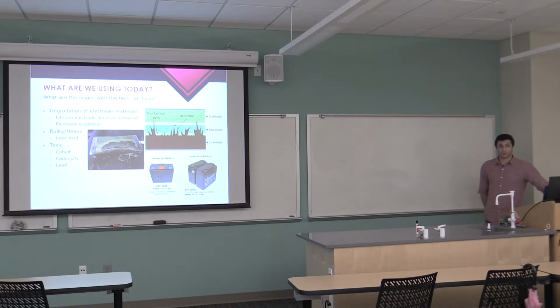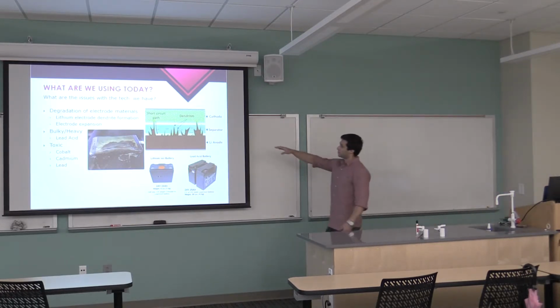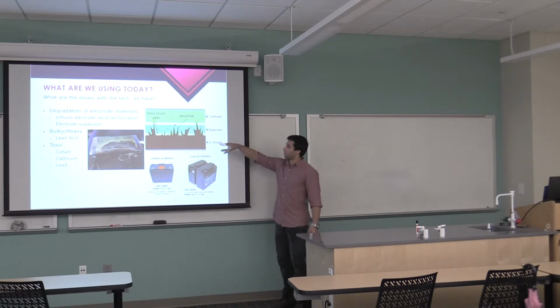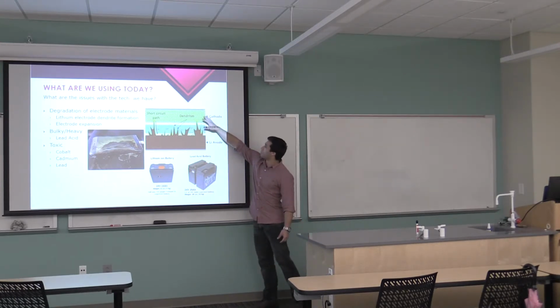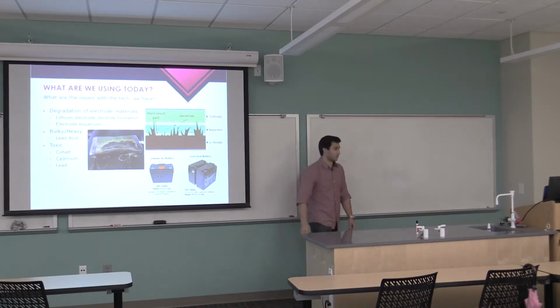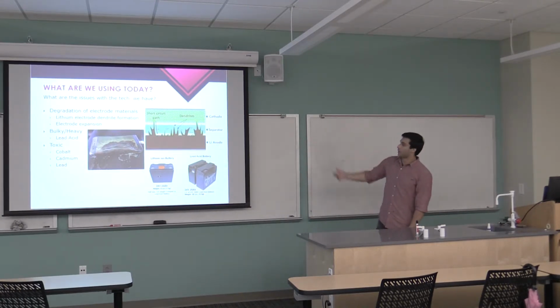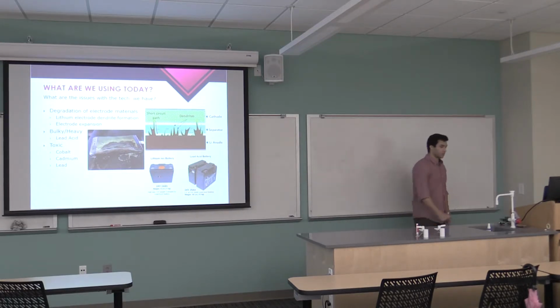And that's because in lithium batteries, you get these dendrites forming here. So basically what happens is when you recharge the battery, the lithium ions have to come back across from the cathode to the anode. And when they do, they can build up these dendrites that can pierce through the separator and cause a short. And that can lead to kind of another Note 7 fiasco that we saw a few years back.